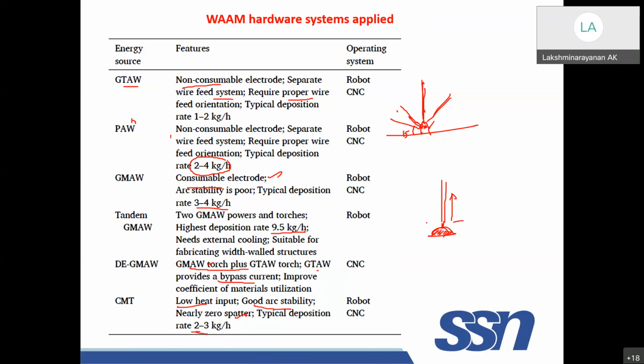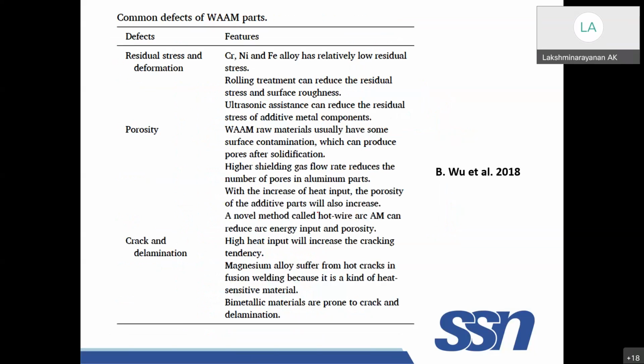But in a few cases like titanium and aluminum, there may be a problem of arc wandering, so the arc is not able to get stable. It depends on the material again, but for most materials CMT is good for WAAM process, right? Now, what are the defects that will be there in the case of WAAM? The first problem is residual stress, the stresses which are built within the material.